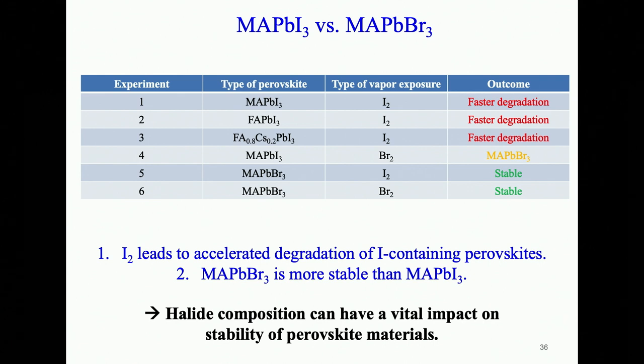from iodine to bromine, we find that the MAPbBr3 shows much better stability against either the iodine (I2) vapor exposure or bromine (Br2) vapor pressure. So this provides us with additional insight that halide composition can indeed have a very vital impact on the stability of perovskite materials.